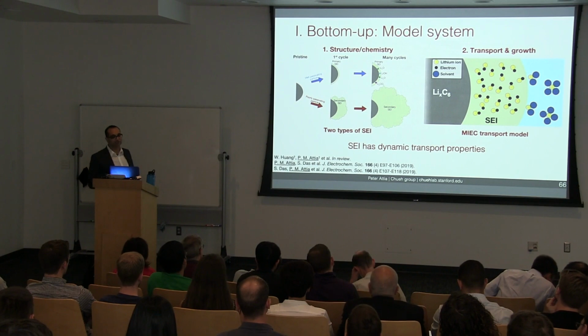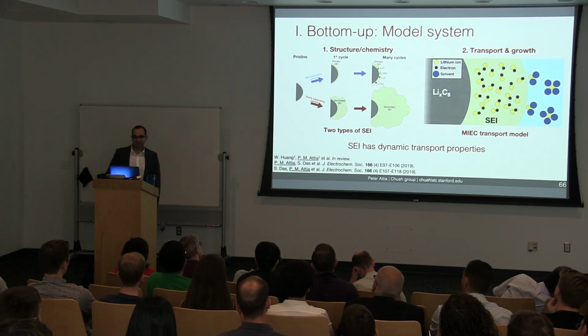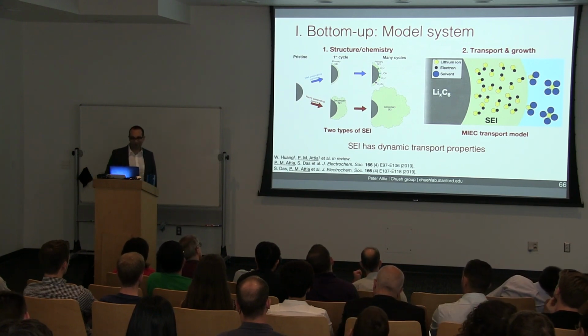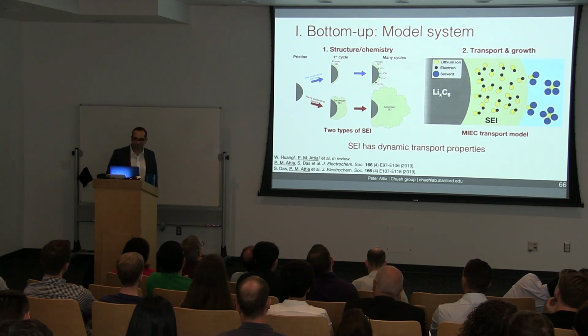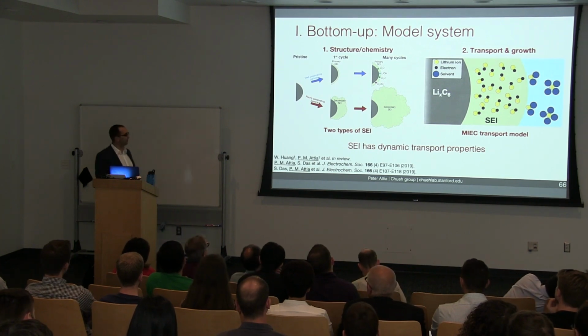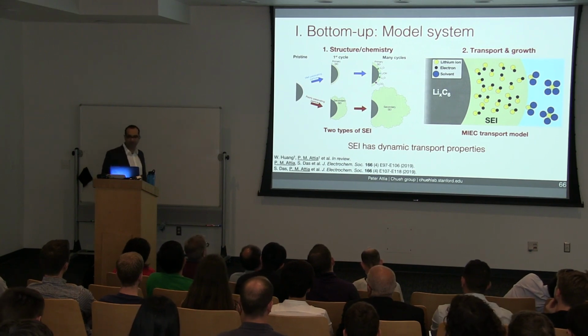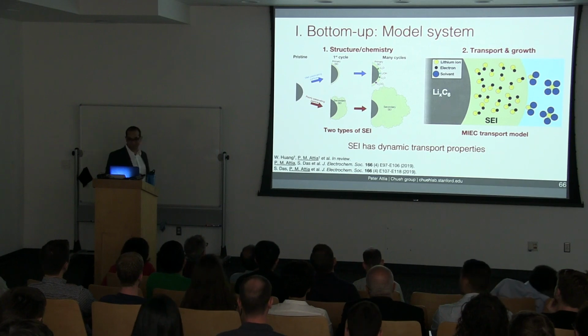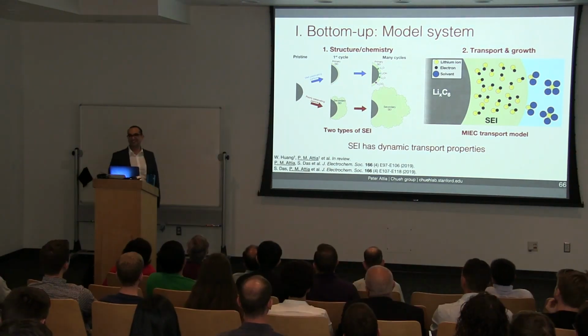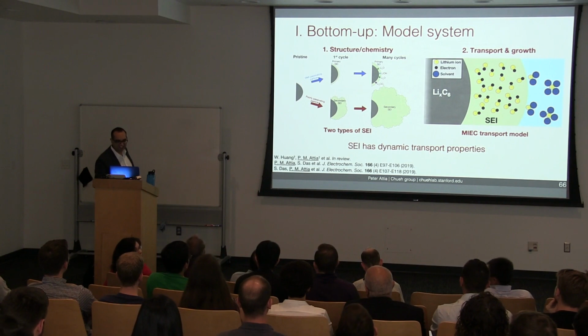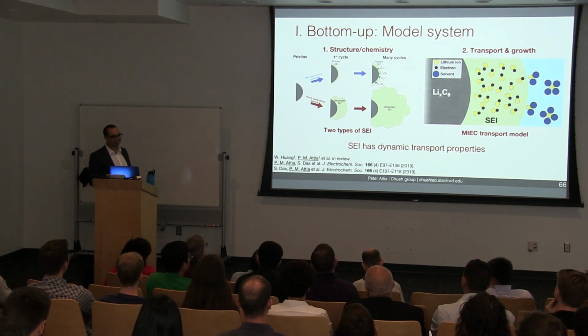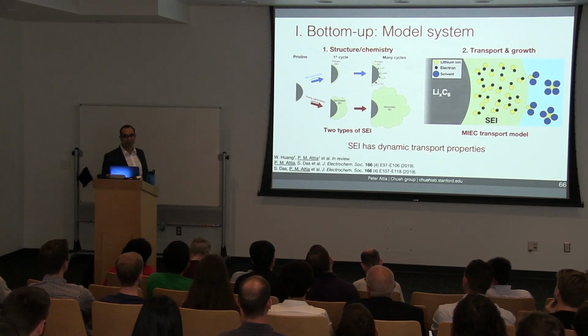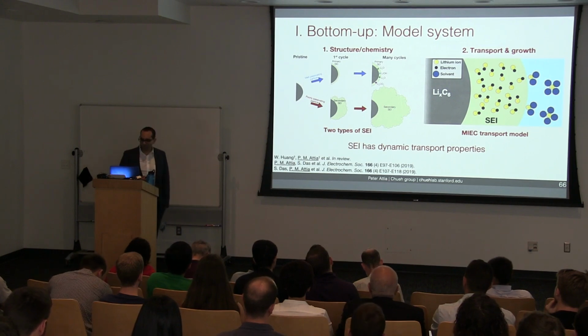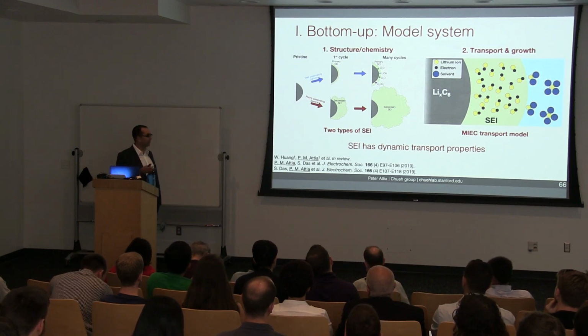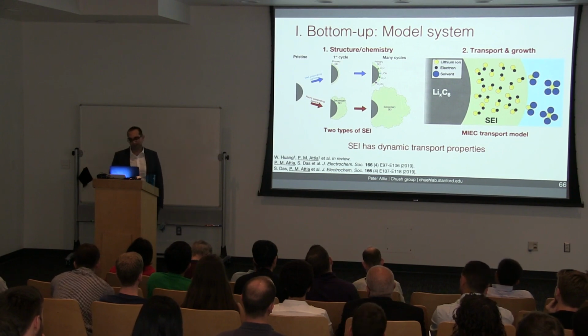Again, the main takeaway from this section is that the transport properties of SEI are dynamic. This holds for the SEI that forms on carbon, as well as many other battery materials. On the experimental side, I think this really motivates the need for in situ and operando interfacial studies for electrochemistry, in situ AFM, and other techniques. We really need ways to see the SEI in action. On the modeling side, I think we absolutely need to understand the dynamic behavior of the SEI, as well as their dependence on potential and concentration. This seems to be the key to understanding important battery degradation modes such as SEI growth.